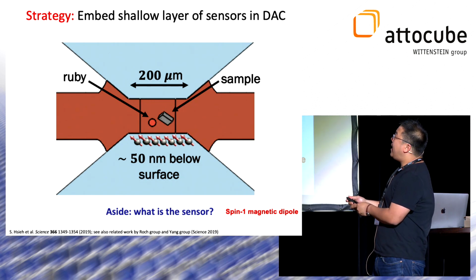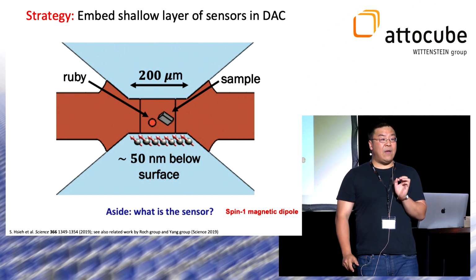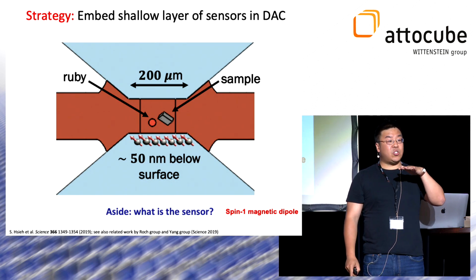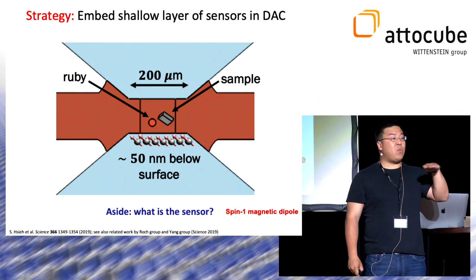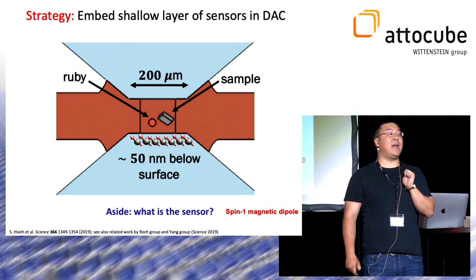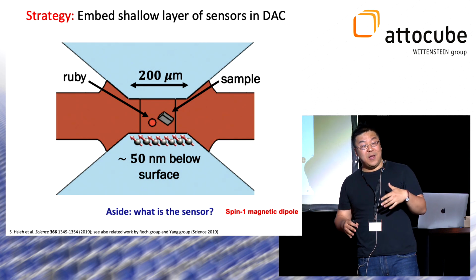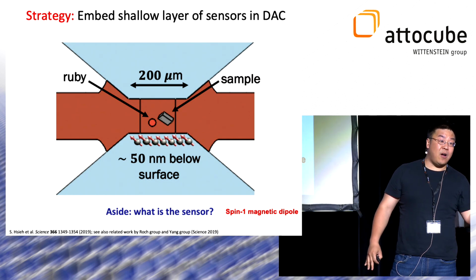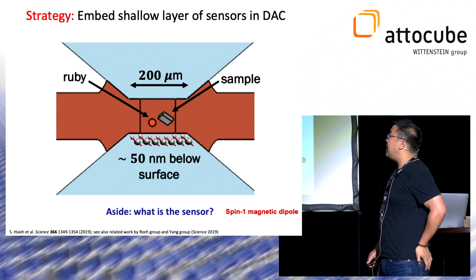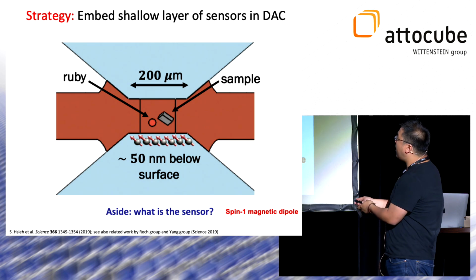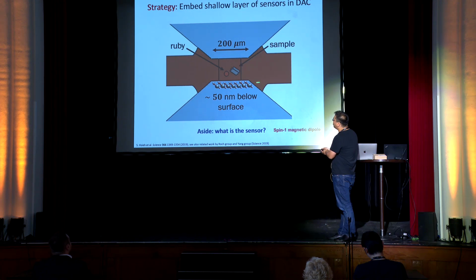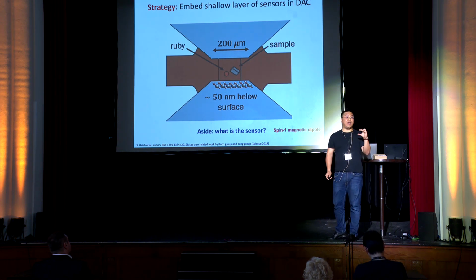The strategy is, it would be very useful if one could somehow embed an extremely thin layer of sensors directly inside the apparatus that is applying the pressure. You will already suspect from earlier talks that you heard in the conference what this particular sensor is going to be, but the idea in my talk is to embed a shallow layer of an ensemble of, in this case, magnetic sensors, maybe about 50 nanometers or 100 nanometers below the surface of the diamond anvil that's actually applying the pressure.